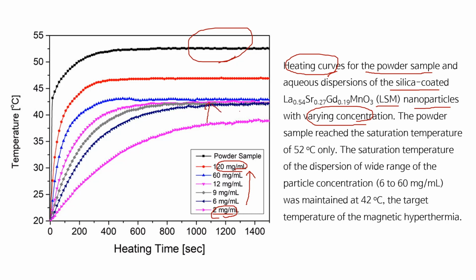However, we can see here, as we increase the concentration of nanoparticles, the saturation temperatures do not change much. Okay. This tells us that the Curie temperature of these LSM particles is around 42 degrees centigrade. The powder sample reaches the saturation temperature of 52 degrees centigrade only, so it does not change much here.